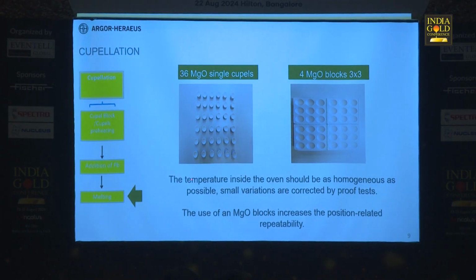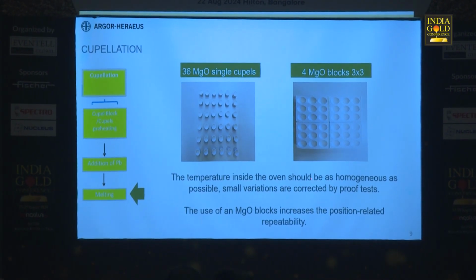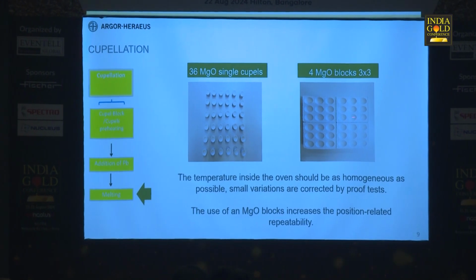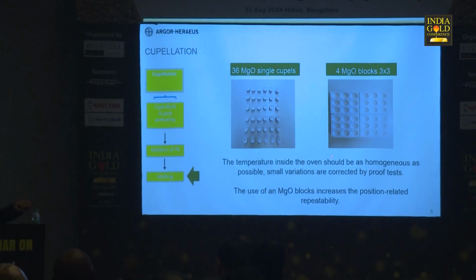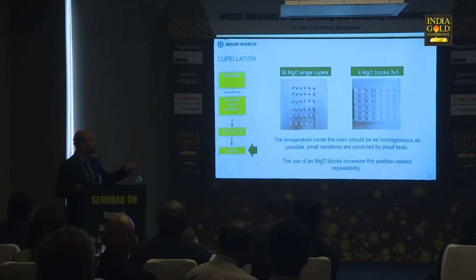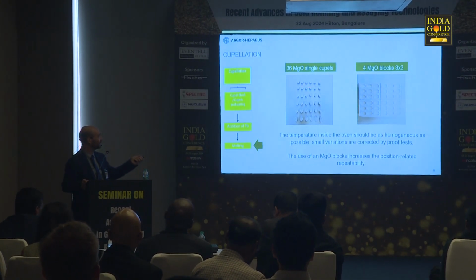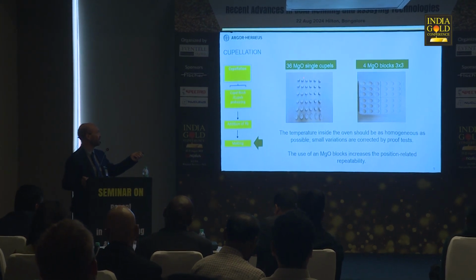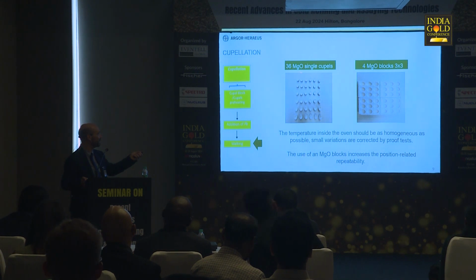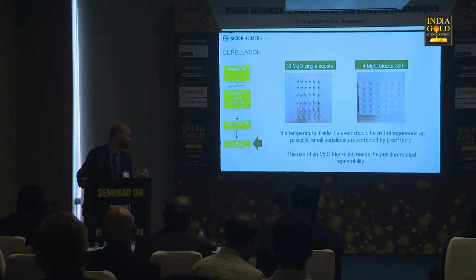This is because the temperature inside the oven, the muffle specifically, should be as homogeneous as possible. But we certainly have small variations from the bottom to the top, from the right to the left of the muffle. We are doing some correction using the proof test, but they cannot do miracles. So we can increase the position-related repeatability using some blocks. You see, they are squared. The single cupels maybe are not in the same line on the x-axis and on the y-axis. So these are giving more position-related repeatability.